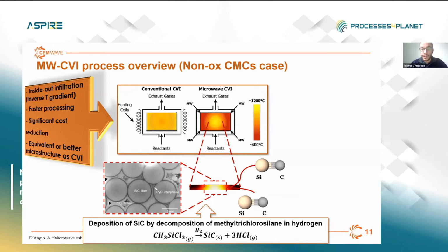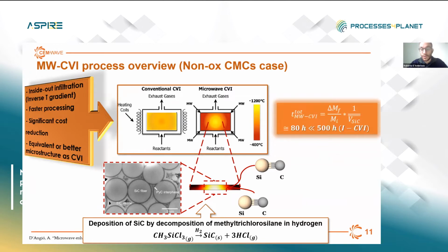In this framework, the usage of a microwave-assisted heating is therefore an attractive alternative due to the peculiar volumetric heating mechanism, which, coupled with surface heat losses, results in an inverse temperature profile in the sample. In this way, the infiltration can start from the heart of the preform, moving towards the external surface as the density of the material increases. So in this way, the premature pore occlusion due to crusting can thus be completely avoided, resulting in a reduction of about 1 order of magnitude in the processing times.